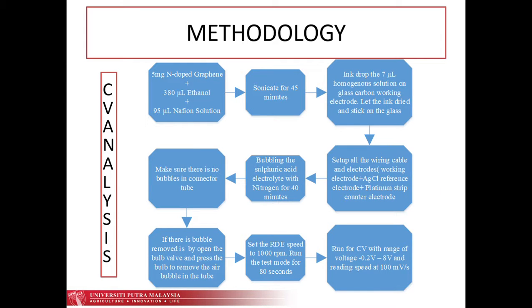For the CV analysis, first of all, we have to prepare the ink to stick on the glassy carbon working electrode. To prepare the ink, we need 5 milligrams of the nitrogen-doped graphene sample plus 380 microliters of ethanol and also 95 microliters of Nafion solution. Then we sonicate the mixture of the powder and the solution for 45 minutes. Then the homogeneous solution will form, and taking 7 microliters of the homogeneous solution, we drop it on the glassy carbon working electrode and let the ink dry and stick on the glass.